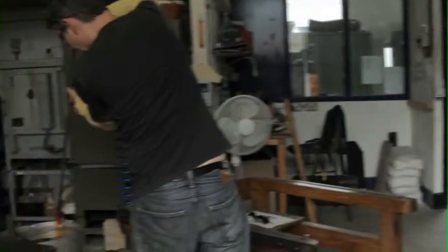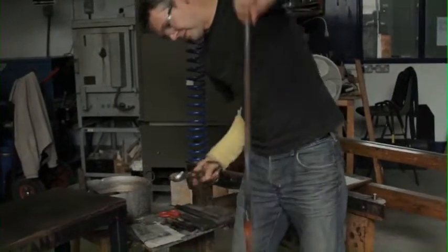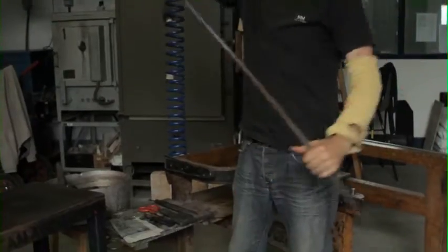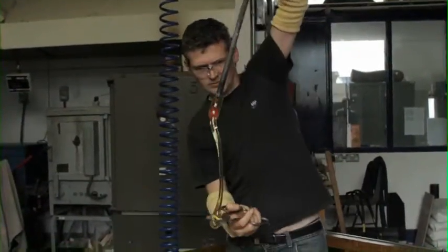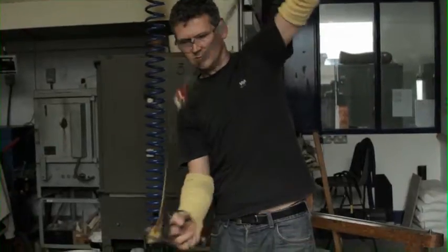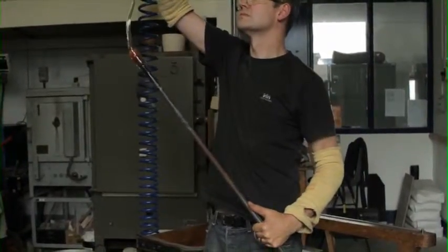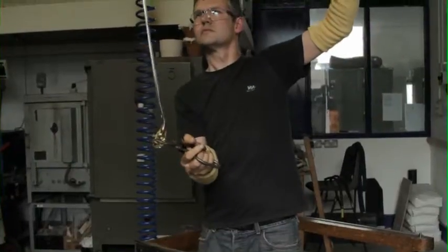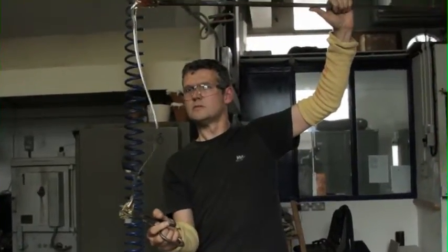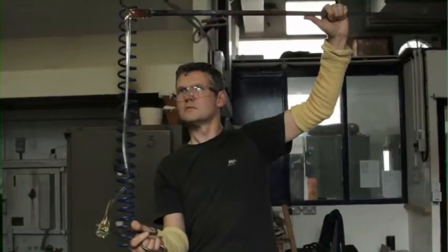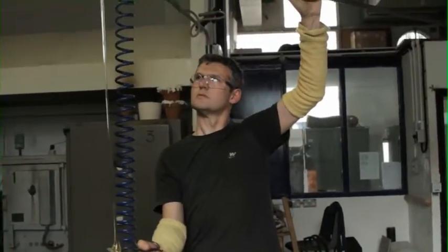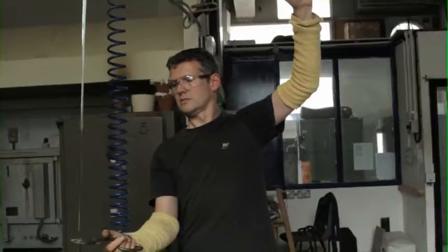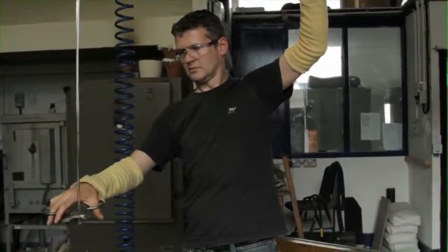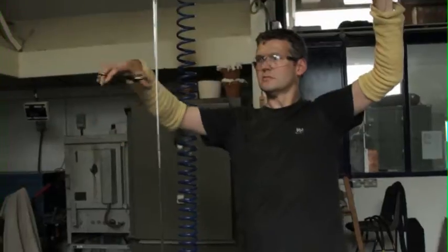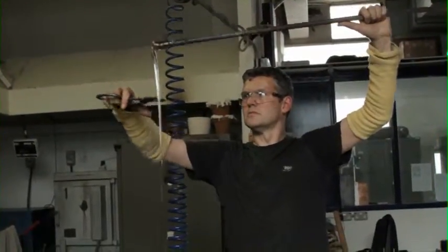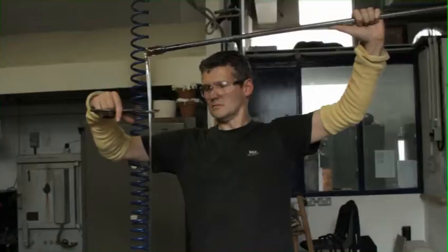I suggested we try again and attempt to effectively glaze the inside of the pot with one hit, putting all the batch together, filling the pot right to the top in one go. On Tuesday the 10th of June we successfully charged 20 kilos of Dr. Fern's batch at 1200 degrees C for 16 hours. It was rather seedy, so we left it for a further 4 hours. After 20 hours it was still seedy, which suggests melting temperatures of 1300 plus, or a soak time of days rather than hours. As we only had a few days to melt the glass and work it, we were running out of time,